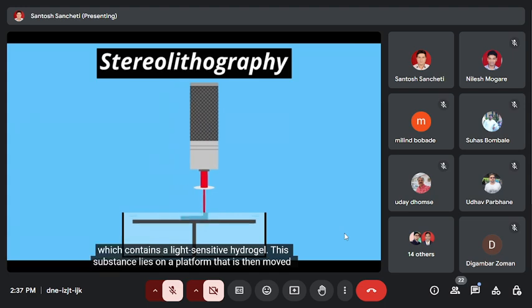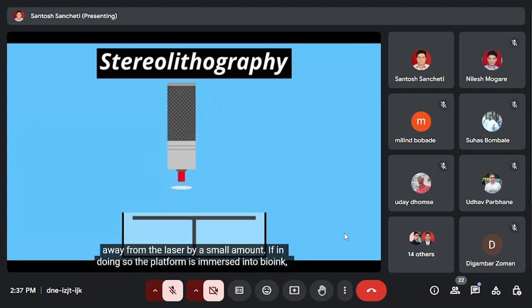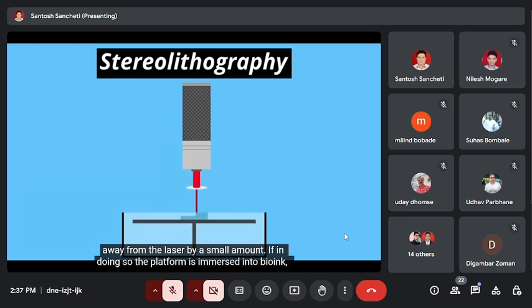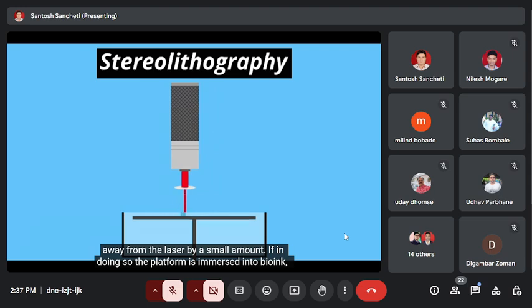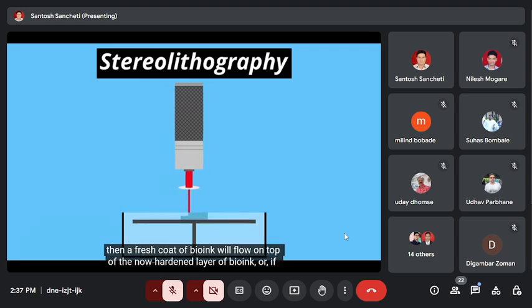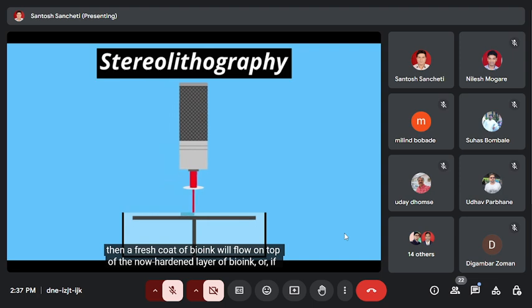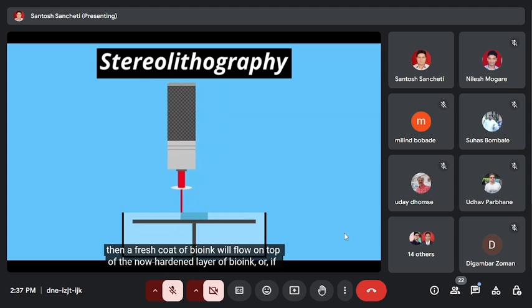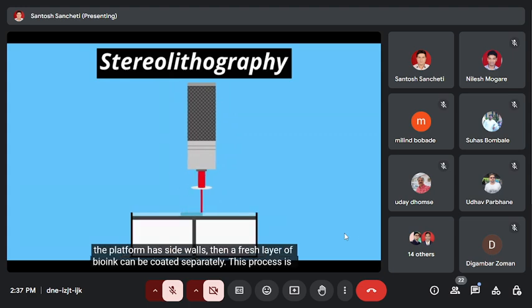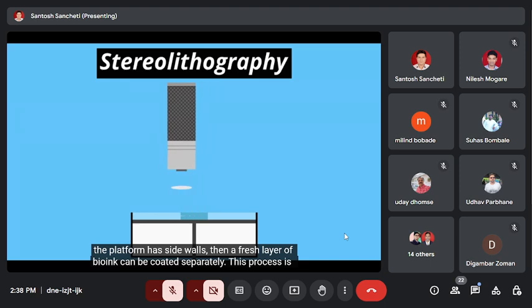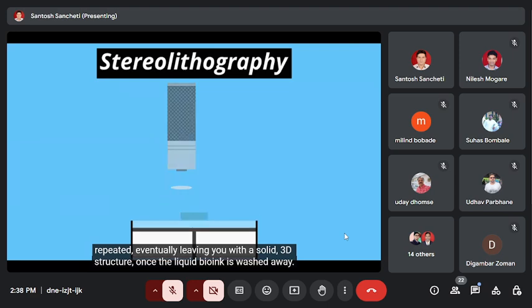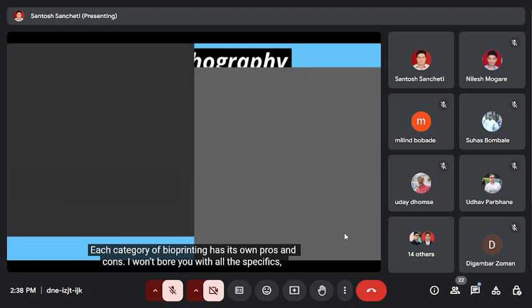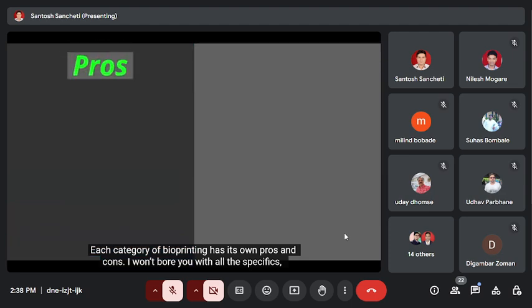This substance lies on a platform that is then moved away from the laser by a small amount. If, in doing so, the platform is immersed into bioink, then a fresh coat of bioink will flow on top of the now hardened layer of bioink, or if the platform has sidewalls, then a fresh layer of bioink can be coated separately. This process is repeated, eventually leaving you with a solid 3D structure once the liquid bioink is washed away. Each category of bioprinting has its own pros and cons.